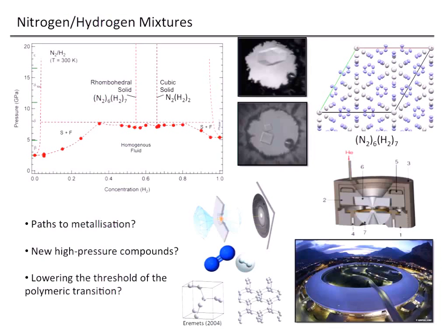The other solid we found in this experiment was this cubic structure, which is just N2H2 twice. Growing these crystals in the diamond cell is probably one of the most fun things I've ever done in the lab, because you change the pressure in the diamond anvil cell with an inflatable metallic membrane. The diamonds are here in the center. Essentially you have a pressure regulator, and you can turn it up or down to grow your crystal or shrink it. You can sit there with your hand on the knob and watch the crystal do this under the microscope. It's really challenging, actually, to get a single crystal like this.